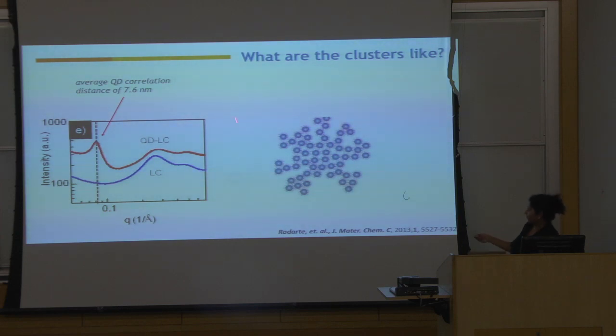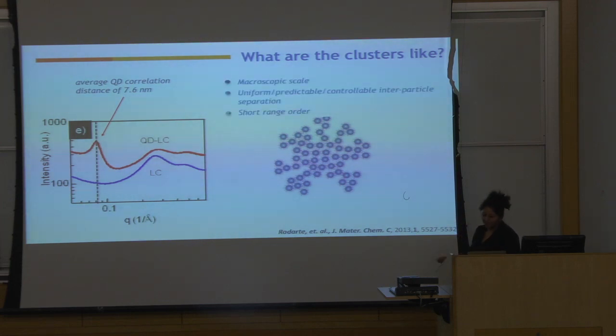So when we came up with a cartoon that represents what the quantum dots might look like in the cluster, they don't form a lattice, obviously, but they do form some sort of an amorphous network like this, where they are in clumps, but within the clumps, they are almost equally spaced from each other. That's kind of nice, because we do want some sort of short-range order. And these clusters are large. They're almost microns, so it's on a macroscopic scale. So we're getting to those amorphous states that we wanted in the first place.